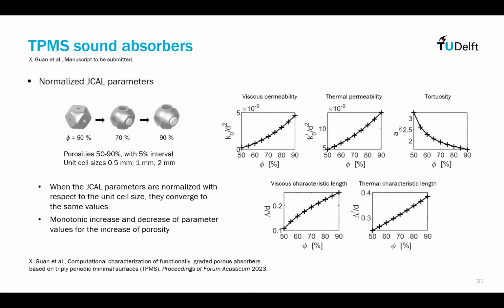If I'm still unmuted, yes, that's fine. I think, though, some of the conclusions you reached could have been reached more easily if you looked at flow resistivity, since classically we know that for a given layer thickness, the lower the flow resistivity, the more resonant will be the absorption coefficient in terms of frequency. And so that explains a lot of why you're getting more resonant. Well, it could explain why you're getting a more resonant absorption spectrum for your low porosity cases.